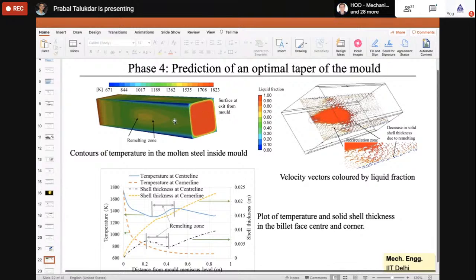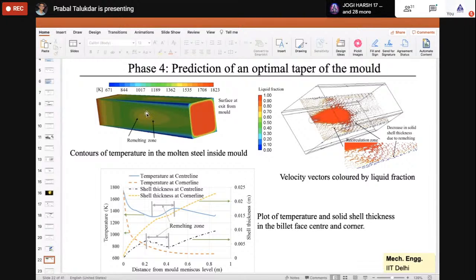This is the temperature distribution shown for the billet, right, which is the inside portion, the solidified liquid. You can see here at the exit of the mold, this liquid is still at a high temperature, somewhere around 1823 Kelvin, and the outer periphery is solidified. But the solidus temperature of steel is higher than that. So these are still at a high temperature, but still they are solid, right? So the deformations you can show here.